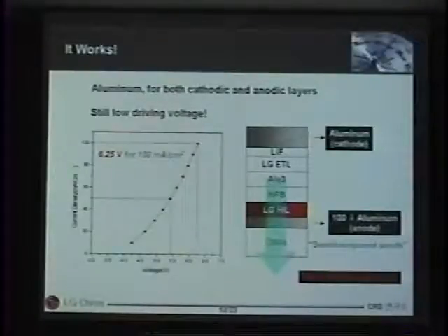We use glass as a substrate, and we deposit just 100 angstrom of aluminum as an anode. And we put LG101 and the conventional device structures with aluminum, lithium fluoride and aluminum as a cathode. So, since we used 100 angstrom thickness of aluminum, it's semi-transparent. So the light comes out through that direction because this is very thin.